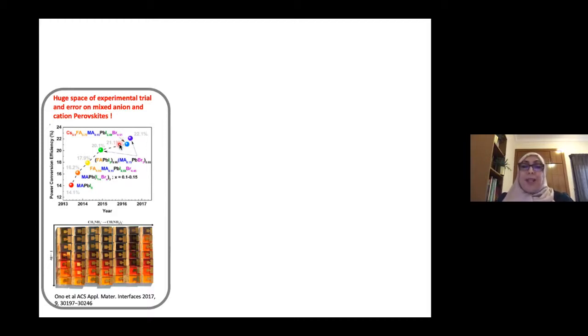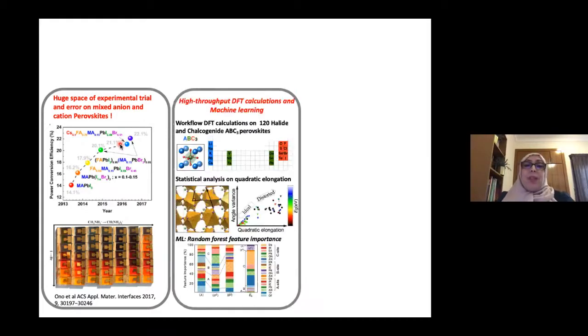It's more the stability that is an issue than the efficiency, to be honest. So then, what we did is that we started to do some high throughput DFT calculations, and then we quickly realized, by looking at the structure of those materials, the lead family and also the chalcogenide family, that it's going to be very, very challenging to analyze the data and come up with answers to our question regarding the stability in particular.